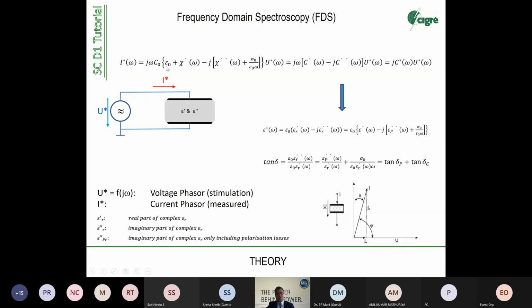Let's see, a response given by the permittivity, and also a contribution given by the conductivity. So both methods consider conduction effects and polarization effects. And from this calculation here, you can derive the complex permittivity, which is epsilon 0 multiplied by epsilon R1 and epsilon R2, the complex function. And in the complex function, you can distinguish between polarization and the conduction part.